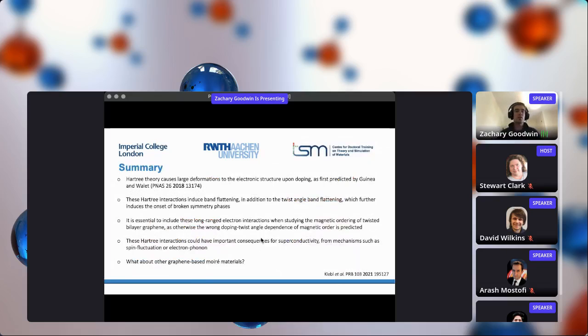Right, so in summary, we've developed an atomistic Hartree theory to investigate magic angle twisted bilayer graphene, which wouldn't really be possible with standard ab initio methods. We found that this Hartree theory causes quite large deformations to the low energy electronic structure, as first predicted by Guinea and Walet. So these Hartree interactions induce significant band flattening, in addition to the twist angle band flattening, which further induces the onset of broken symmetry phases. And it appears that these interactions are essential for understanding the twist angle and doping dependence of broken symmetry phases in twisted bilayer graphene. That pretty much brings me to the end of my talk, so thank you for listening.